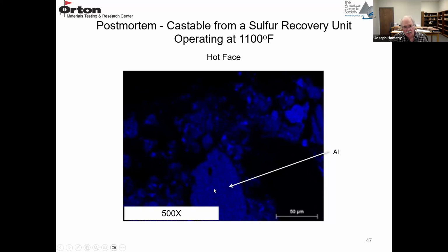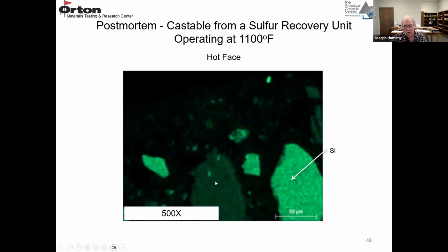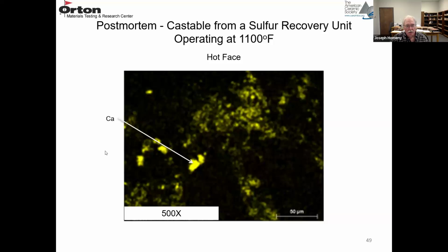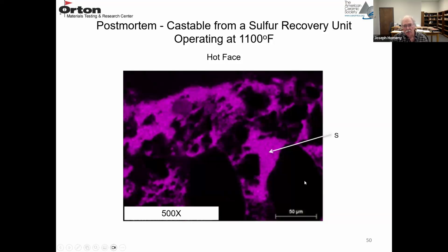So you can clearly see the aluminum oxide aggregates, the coarser one here, finer ones in the blue color. And then silicon is in the green here. So these really bright ones are quartz or cristobalite. And then this one is not as bright, but that's the alumina silica aggregate. And the calcium is in the matrix. These brighter calcium spots are probably the calcium sulfate that's forming. And then the purple would be all the sulfur infiltrating through the matrix.